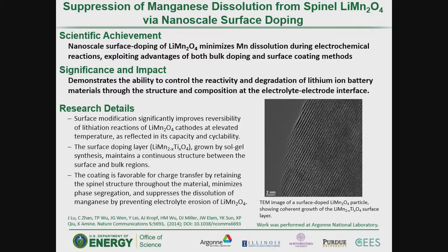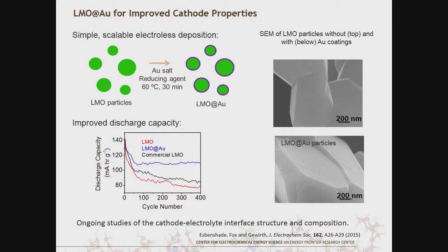This is some work from Amine's group. What he did was add coatings on LMO, titanium-containing spinel coatings. He found that with these coatings on the surface, he could effectively suppress manganese dissolution. So this is one way dissolution of manganese can be controlled.